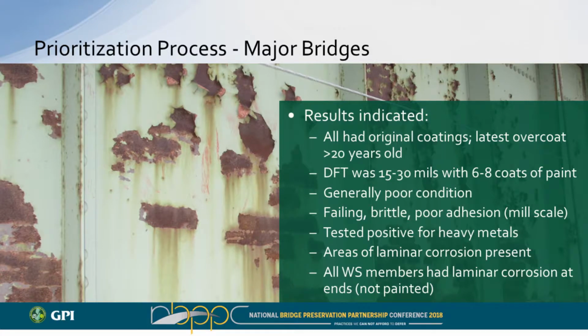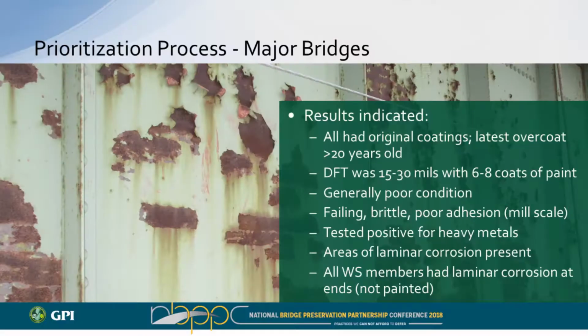The coatings were generally up to about 30 mils in thickness with 6 to 8 coats of paint. Some of them on the horizontal surfaces, we got on up into the 50, 60 mils range, and in some cases, the low teens for the number of coats. Overall, the coatings were in bad shape. The picture represented here is very representative of their major structures throughout.